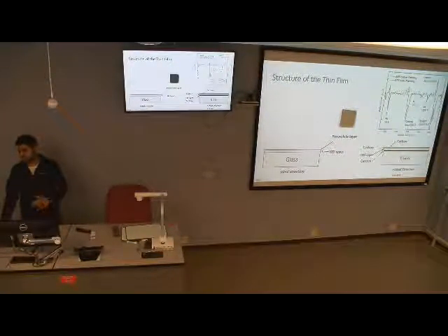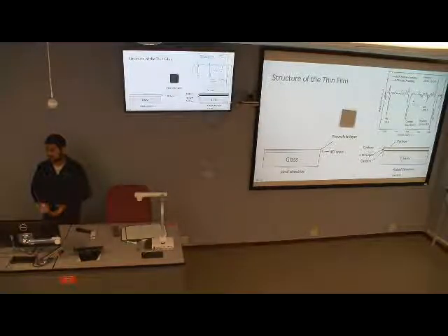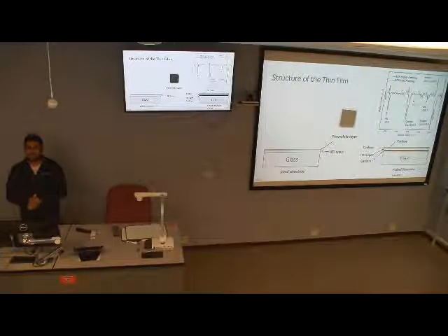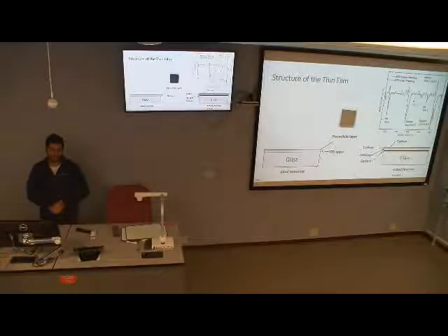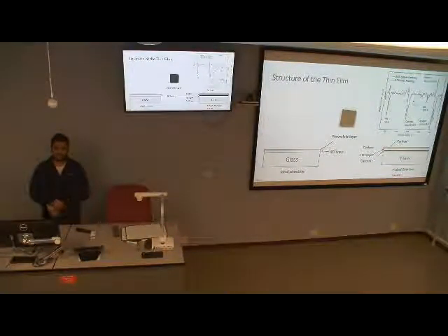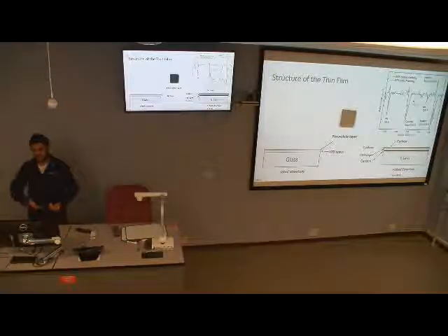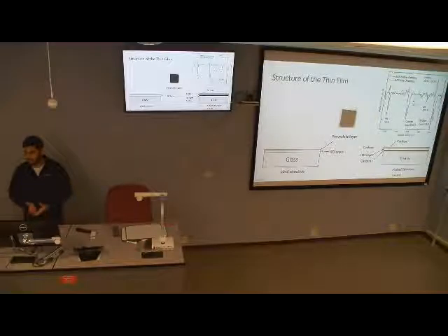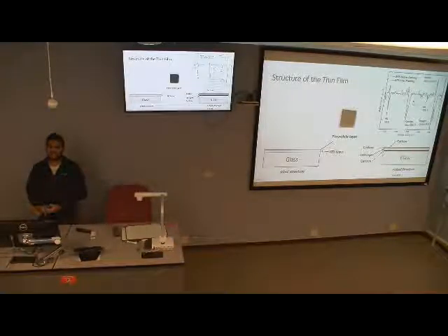So we did the ambient pressure synthesis using a substrate coated with indium doped tin oxide, and that substrate we cleaned, again, at ambient conditions. So we couldn't remove all the carbon impurities. The substrate itself can contain some carbon, and the perovskite layer, after and during the synthesis, can be contaminated with atmospheric carbon dioxide and oxygen.